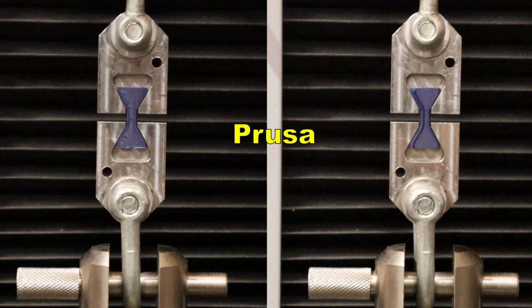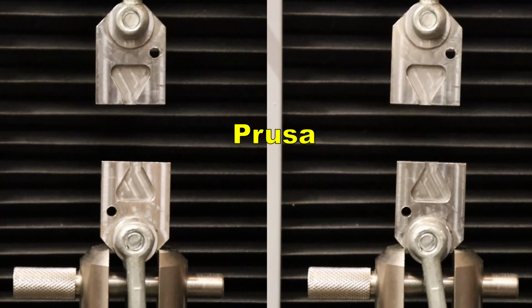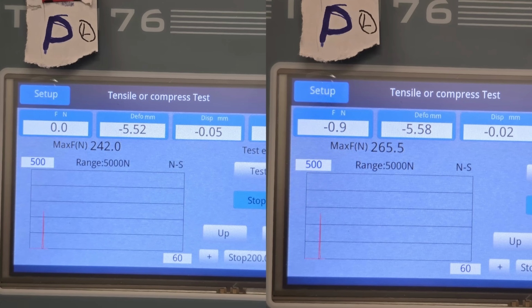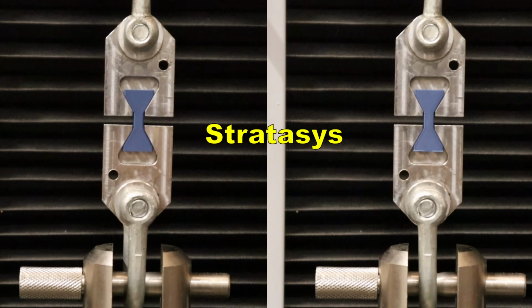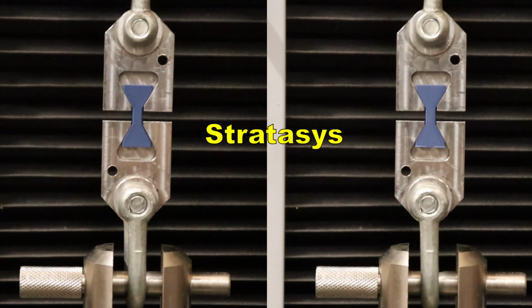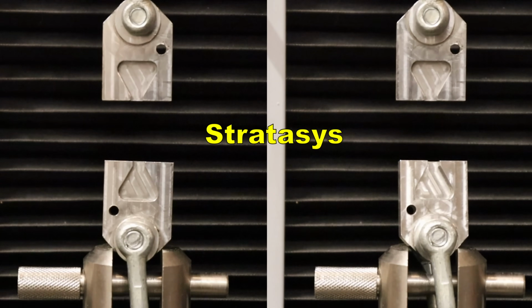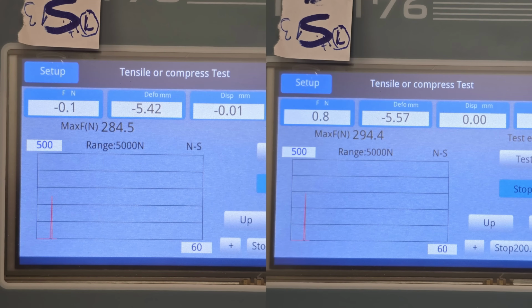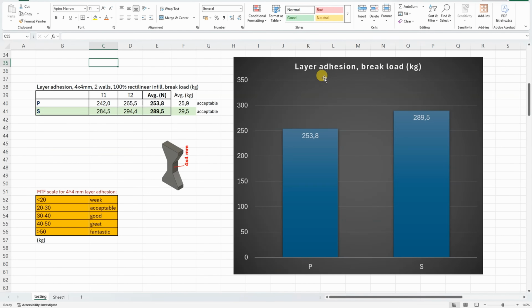Layer adhesion, vertically printed. The maximal force and the graph. And this is Stratasys. And again the maximal force in newtons. This is an important property of any material, and here I converted the newtons into kilograms, and this is my table with the rating for these test objects, and we can see in both cases this is acceptable layer adhesion, but Stratasys is better even if it was printed at a much lower temperature.